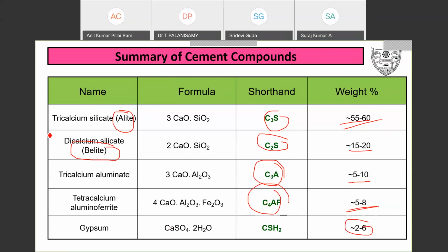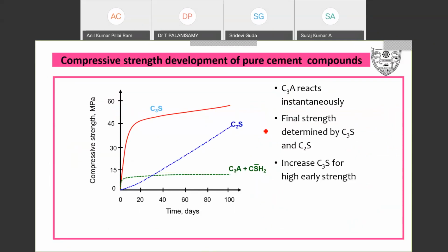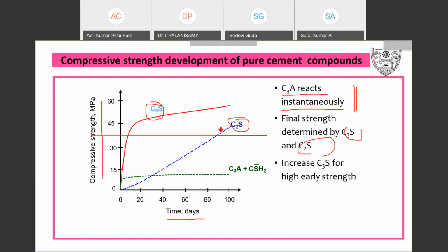Now, tricalcium silicate, alite and belite, are very important components in the manufacturing of the cement. Now, this is the compressive strength development of pure cement compounds. Look at, on the x-axis we have the time, days. On the y-axis, we have the compressive strength. Look at C3S. C3A reacts instantaneously, immediately it reacts. Then the final strength is determined by C3S and C2S. Then increasing C3S increases the early strength. So these are some of the compressive strength developments.